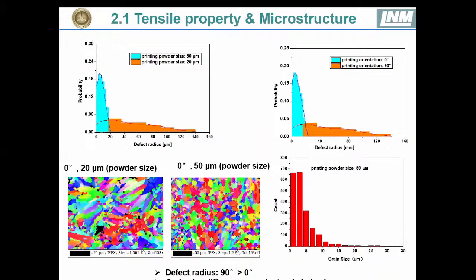And of course, the microstructure for the material manufactured with different powder sizes are also observed and also shown in this figure. And it can show the distribution of the defect size, and also the distribution of the grain size. And in general, the defect of the specimen manufactured with 20 microns is larger than those with 50 microns, and also the distribution from the specimen manufactured for different orientations also shown here.